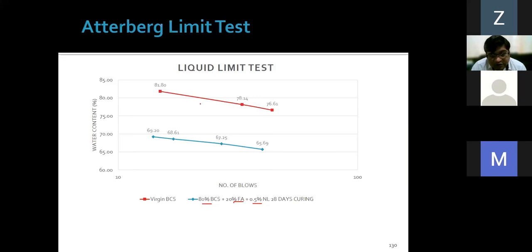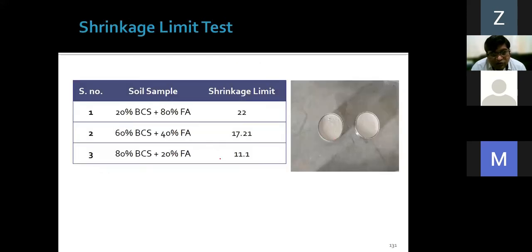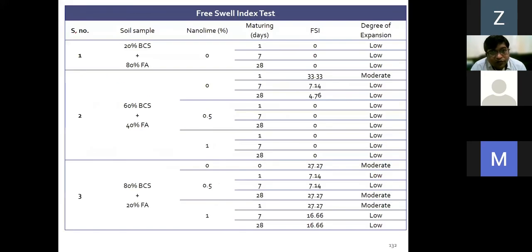You can see that the liquid limit is reduced drastically. Shrinkage limit has also reduced. Free swell index we have also tried with various combinations, right? With 60% soil, 40% fly ash, and 1% nano lime, we can see that the free swell index was 0. So that is the power of nano things. Traditionally you need to add 12% to 15% lime, but when converting it to the nano level, only 1% is sufficient. So that is the power of nanotechnology.